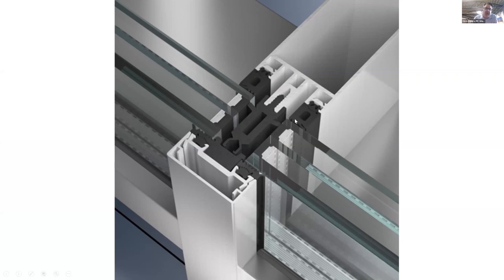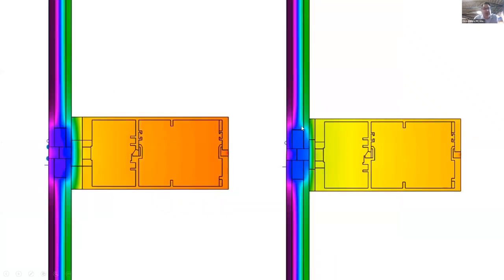But what you need to understand is that the gaskets on a well thermally broken aluminum system are less dense than the structural silicone. And oftentimes what people try to do is make the glue line thickness of that silicone as small as humanly possible. So if the aluminum, the highly conductive material in this facade, is closer to the face of glass, it doesn't perform as well. So when we start looking at our systems, here's two different analyses we did to check this in our office because we were baffled at why we were getting the value.